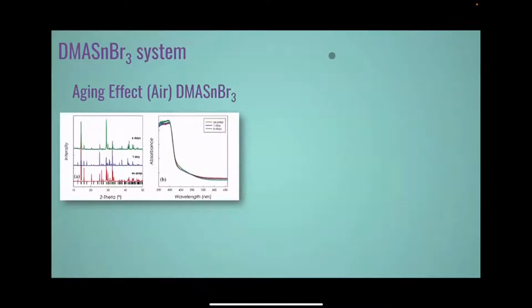The point is that we then investigated the aging effect of these materials, in particular of the dimethylammonium tin tribromide. The aging was first done by exposing these perovskites to air. Here you have tin 2+, okay? Tin 2+ is easily oxidized to tin 4+, and you destroy the perovskite. Anyway, after 6 days of air exposure, and trust me, in Pavia, where I live, we have a very high humidity, around 40% in this season and even more, in moist air the perovskite diffraction patterns were fine. Optical absorption was still fine.